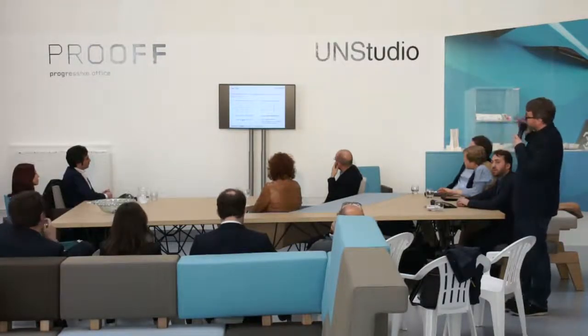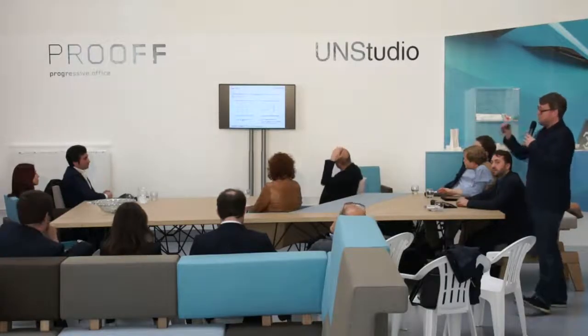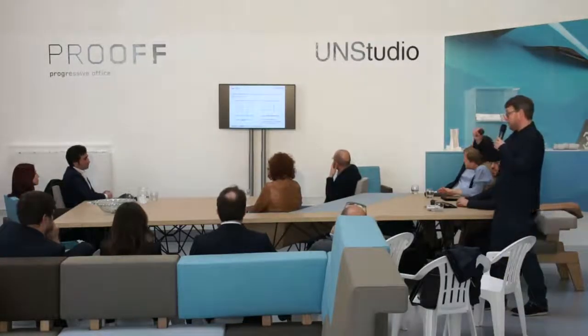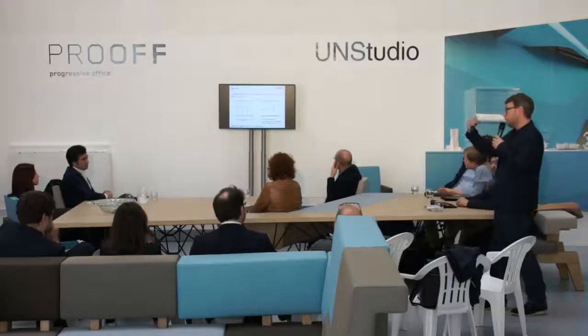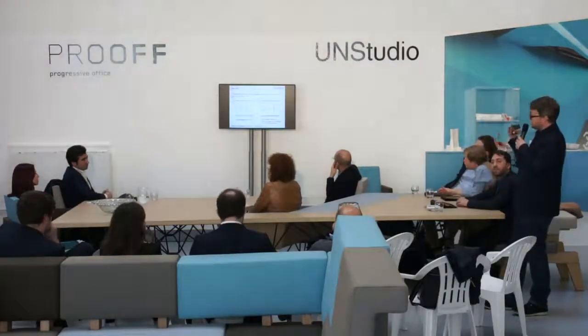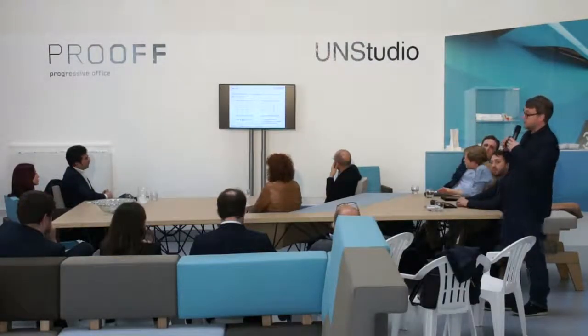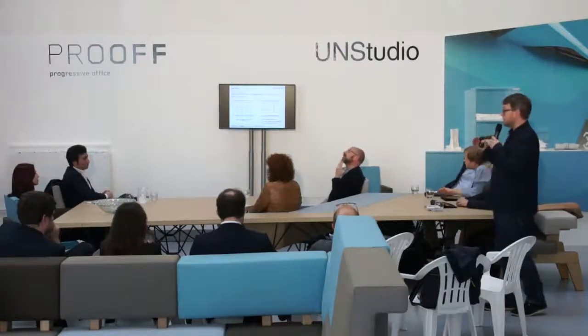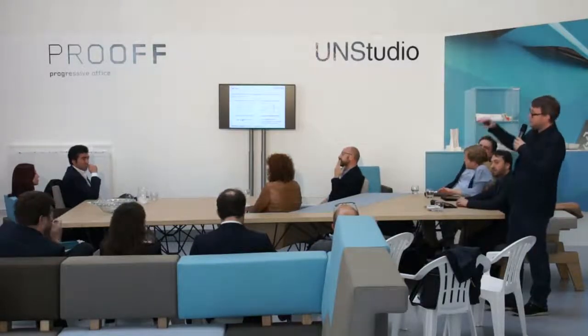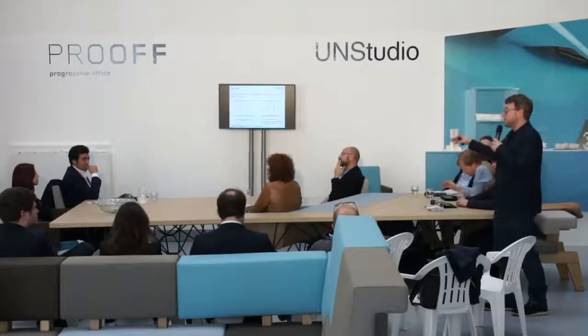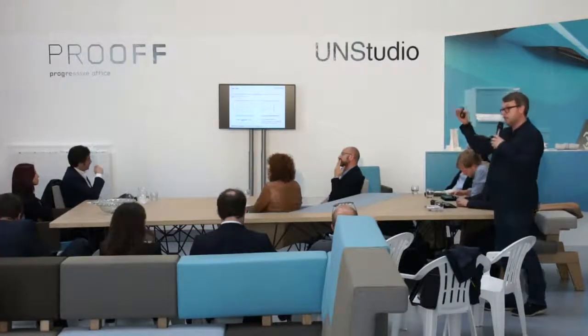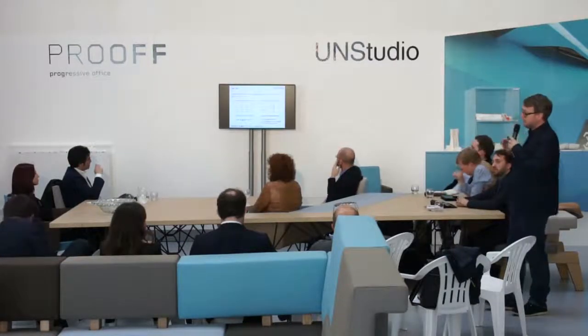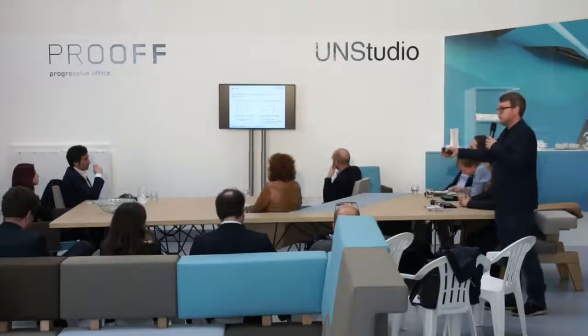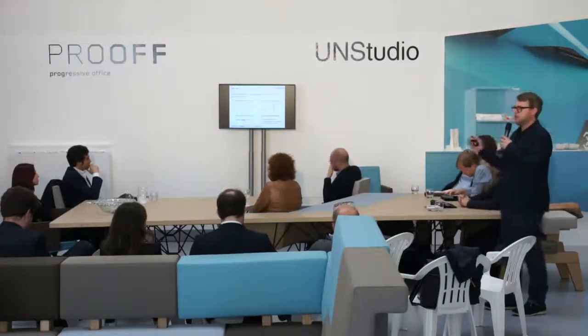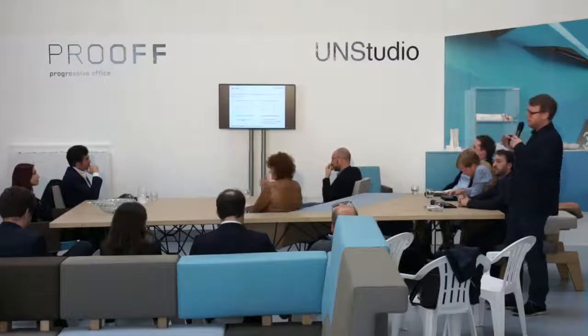With Gorilla Glass, what we found is that by failing the middle piece of glass, by sandwiching it between two very thin pieces of glass, we broke the middle piece, but in fact, the containment of the very, very high strength skin on either side of this regular piece of glass enabled it to continue to carry load to 4 times, 5 times its breakage load. So it has a very, very high post-breakage behavior, which then leads you to the idea that, well, that's interesting. Where do you need something that has a very, very high post-breakage behavior?